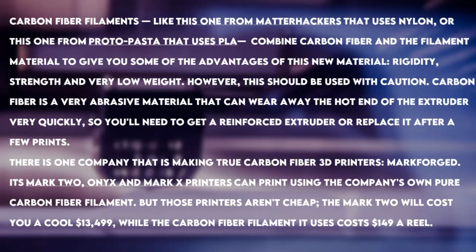So this has to be used with care. As you can see, carbon fiber is a very abrasive material that can wear away the hot end of the extruder very quickly, so you need to use a reinforced extruder or replace it after a few prints. Otherwise you can use some nozzles like I mentioned, the ruby crystal, or the hardened steel, or the tungsten, I mean the titanium one also. Or otherwise you can replace it after a few days. So that all depends upon who you are.